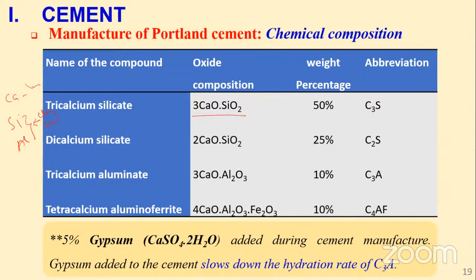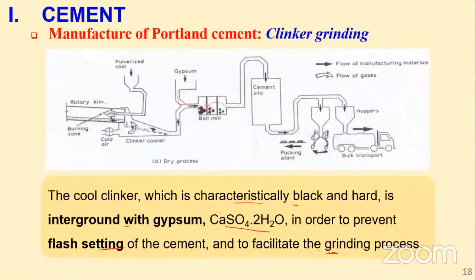All right, now, so we are saying in this last step here that there is fusing at 1450 degrees centigrade, sintering, clinker. They fuse. So the calcium from clay, the silica, the alumina, they combine.